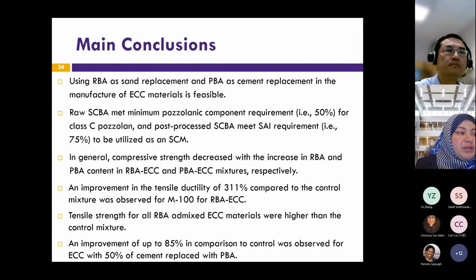We saw an improvement in the tensile ductility of 311% compared to the control mix. The tensile strengths of the raw bagasse ash admixture were higher than that of the control mix. An improvement of up to 85% was seen in comparison to control when observed with 50% cement replacement of bagasse ash or processed bagasse ash.